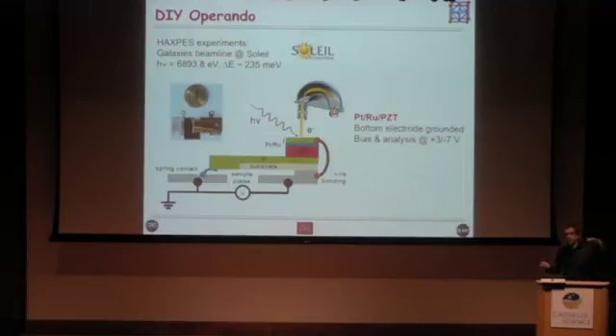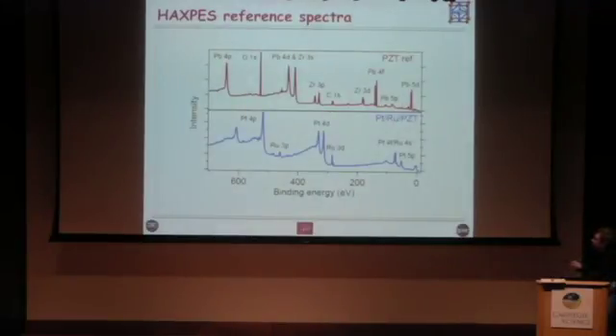And this allows us not just to probe that buried interface, but also to get the response, the chemical and electronic signature, under bias. In other words, under real operating conditions. So here's the first results. This is a reference spectrum without the top electrode. All the usual core level peaks are there. We put the top electrode down, and then effectively, on this scale anyway, we've almost completely attenuated the signal coming from the PZT. This is just to underline the need for probing down below that electrode and using hard X-rays.